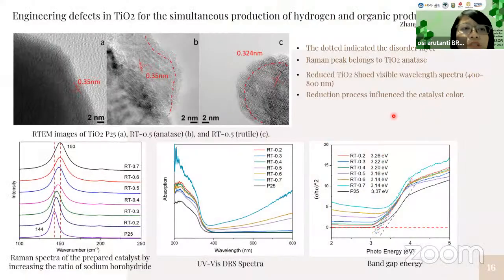And the second one, I chose this paper, Engineering Defect of TiO2 to produce hydrogen, by Zeng et al., published in Applied Catalysis B: Environmental. Here they show us how to produce a metal-free catalyst with high photocatalytic activity. They use TiO2 P25, and then they use sodium borohydride as the reduction agent.